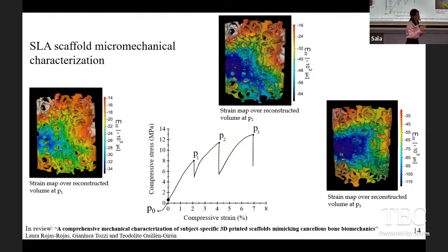And also, we wanted to see or study where strain was going to be accumulated, because remember, this is going to be used for bone cells growth under mechanical stimulation. In literature, it is found that cells tend to focus in the areas where the strain is higher, and this is where also the mechanical signals are higher. So it was a nice result for us.